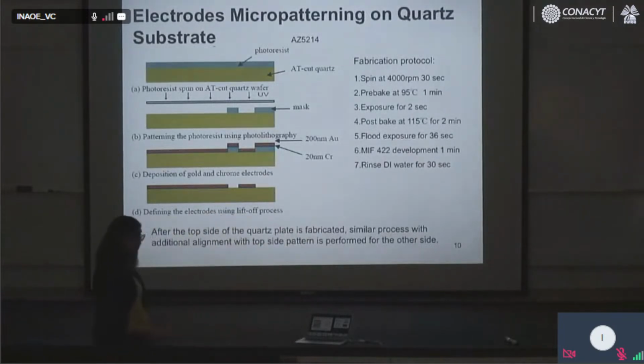Now, if you know the MEMS technique, I will explain a little bit the fabrication steps of this sensor. It's very simple because, as I said, my lab is not so sophisticated, and the student cannot do very small dimensions of devices because the whole fabrication is based on the lift-off technique. For the lift-off technique, you use the quartz crystal substrate, and you use the photoresist. And generally, for the lift-off technique, you use AZ photoresist, which is an image reversal photoresist, and you use UV light. You use the mask. As I told you, we print the mask with the printer, black and white. We didn't buy a regular mask. Our mask with the printer may be $50.